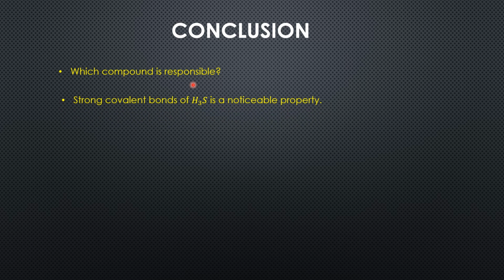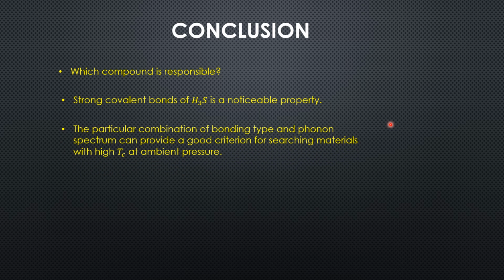Also, one of the noticeable properties is the strong covalent bonding in H3S, which is in agreement that a metal with high Tc should have strong covalent bonding and high frequency modes in the phonon spectrum. So we can say that the particular combination of bonding type and phonon spectrum can provide a good criterion for searching for high Tc materials which are superconductors at ambient pressures.